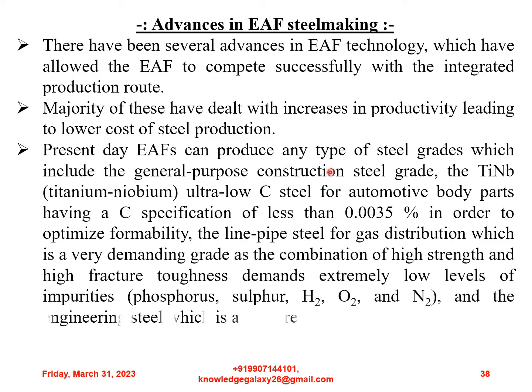Present day electric arc furnaces can produce any type of steel grade, which includes the general purpose construction steel grade, the titanium niobium ultra low carbon steel for automotive body parts, having a carbon specification of less than 0.0035% in order to optimize formability, the line pipe steel for gas distribution, which is a very demanding grade as